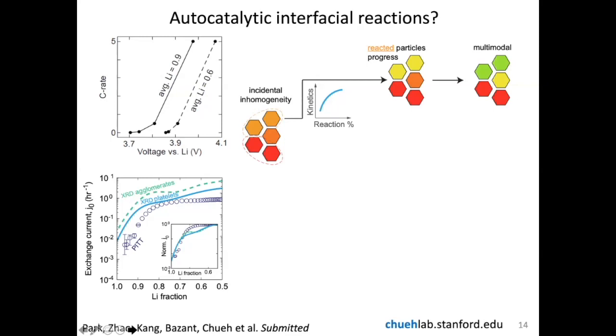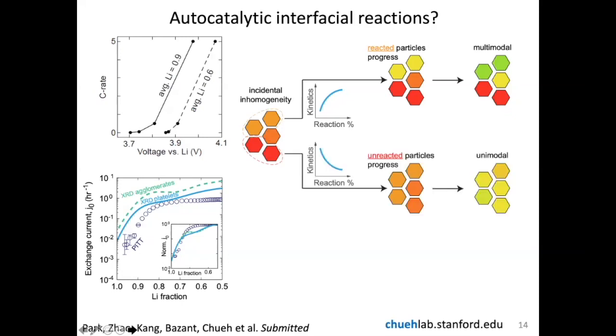So as I remove lithium from the material, the kinetics is getting faster and faster and faster. This means that lithium will be preferentially extracted from particles that already have less lithium to begin with. So this causes the compositional heterogeneity between particles to grow. And this can explain the multimodal distribution of lithium as you delithiate. But as you lithiate, so as you discharge the material, then the kinetics goes in the opposite direction. As you relithiate the material, the kinetics is getting slower and slower. So what this means is that the incidental heterogeneity will actually begin to decrease in the material. So this leads to the unimodal behavior.